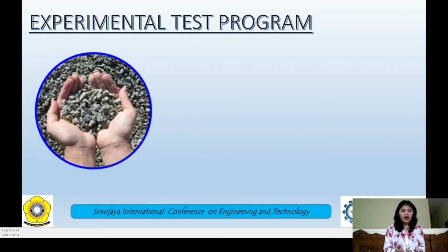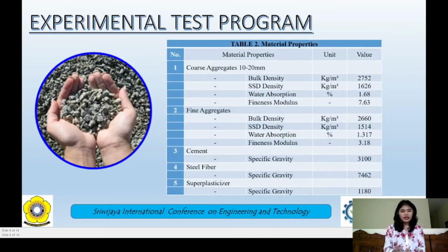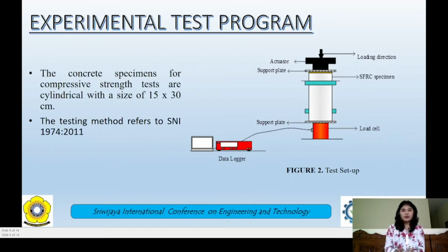The concrete materials are analyzed to determine the characteristics as the basis for determining the mixture ratio, and the material tests include sieve analysis, bulk density, SSD density, and others. The concrete specimens for compressive strength tests are cylindrical with a size of 15 times 30 centimeters. The testing method refers to SNI 1974:2011. The test setup is as shown in figure 2. This test measures the load on each specimen using a load cell connected to a data logger.